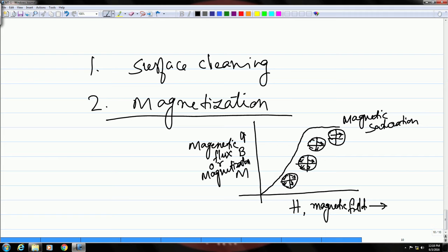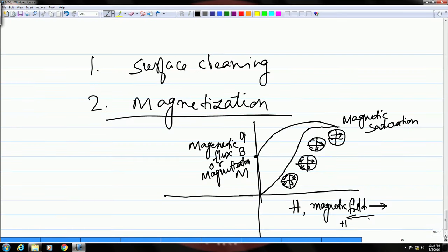Okay. Now, if you reverse the field, if you change the direction of the field, if you do field reversal, then while coming back, it will not follow this same curve; rather it will follow a curve like this. Now at this point, although your field is 0, it is still having some magnetic flux, it is still having some magnetization. That means it is retaining some of the magnetization which was provided in the beginning, and that is why this point is known as the remanence. If we denote that as R,